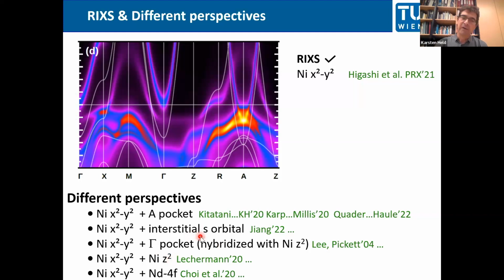And there are also further calculations. So this simple picture with just this x squared minus y squared orbital is, well, indirectly supported by RIXS experiments and their interpretation, which finds that actually most of the holes go to this x squared minus y squared orbital. Okay, but anyhow, there are very different scenarios in the literature. That's the minimal scenario, and let's see how far we get with this kind of description.